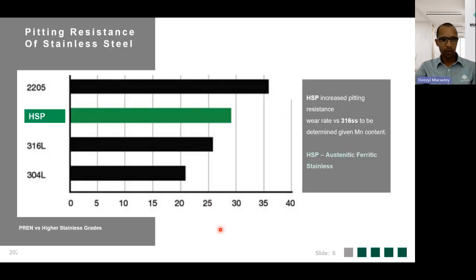It was interesting to see that the HSP was actually more resistant to pitting than 316, but when we installed the unit on site, after 3 days of operation, it started pitting, which just went against what we tried to achieve. But it must also be noted that your PREN should not be the only consideration to determine the pitting potential of a particular stainless steel.